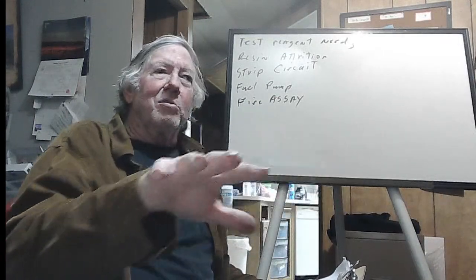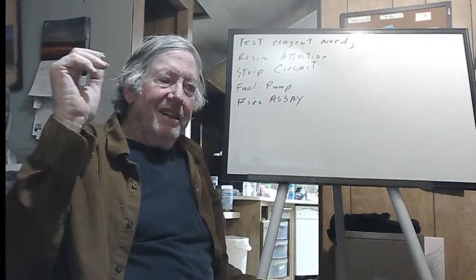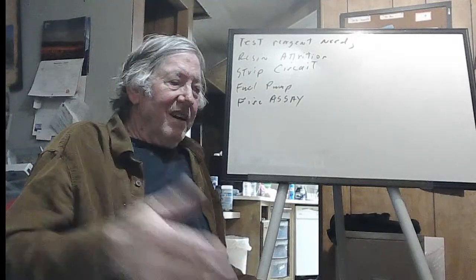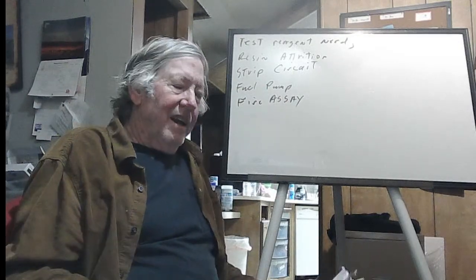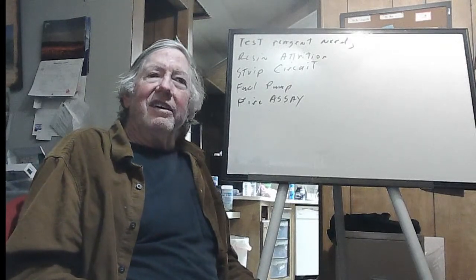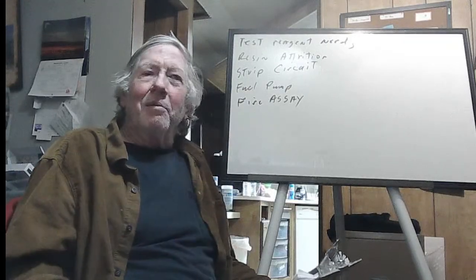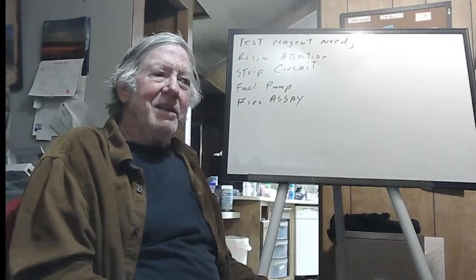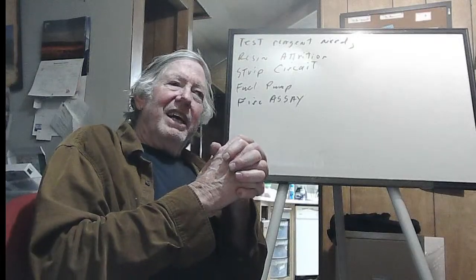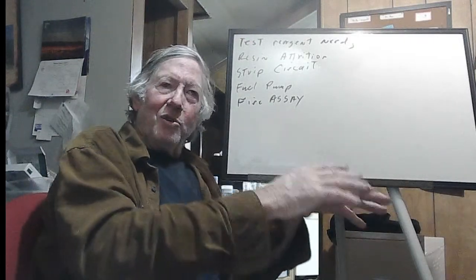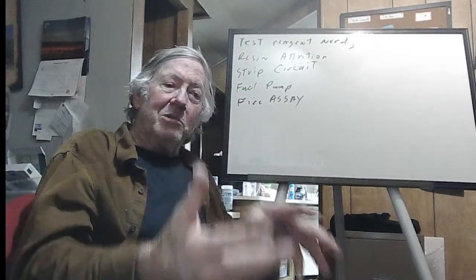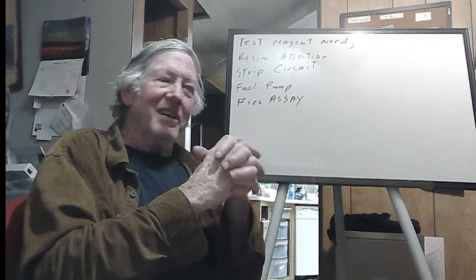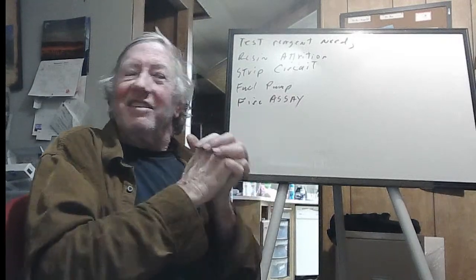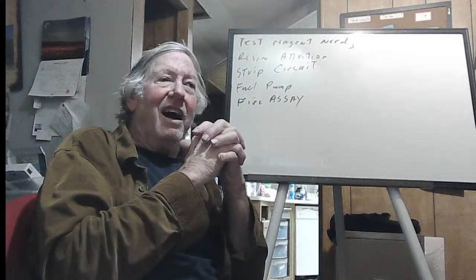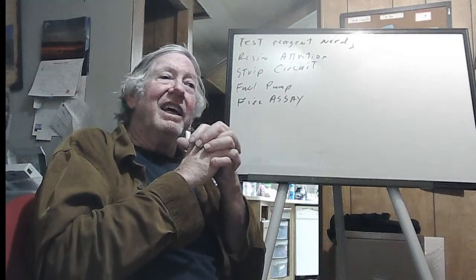All of these that are cooked well, the slag works fine. You fire assay it, it's basically a litharge flux. The flux is nice and fluid. There are no little sparks floating around, things like that. Works fine. But that last serious cook seemed to lose a couple of percentage points, 3 or 4% of the gold. So it seems to me the simplest way to do this is just bring it up to 600 degrees from the dry as quick as you want, smelt it, and then add 10 to 15%. Say, okay, I lost 10 to 15%, but since I know I lost 10 to 15%, and this is just a number, I can do that. Obviously, you wouldn't want to lose 10 or 15% if you're smelting for production.